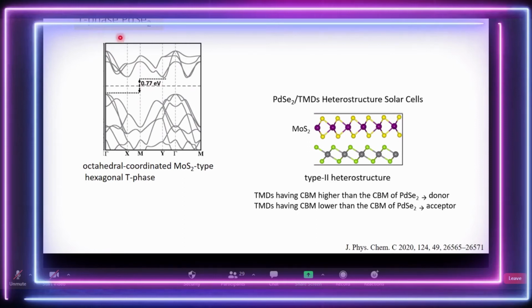So the T phase or hexagonal PdSe2, if you use it directly as a photovoltaic material, is going to be very, very poor, because it's not going to absorb solar radiation effectively like a material with a 1.3 eV gap. But the advantage we have is that it has a very, very high mobility. So the concept that came in is, why don't we use heterostructure solar cells? So you pick up your PdSe2 and then form a heterostructure by picking up another transition metal compound, MoS2.